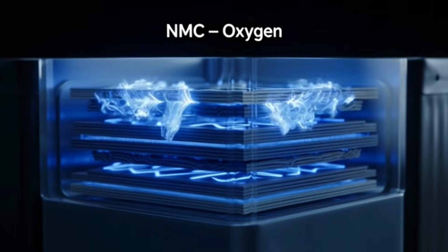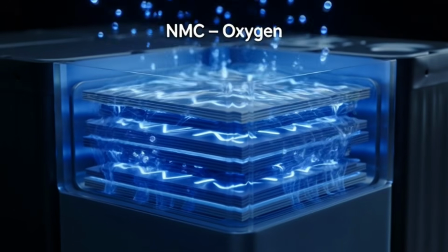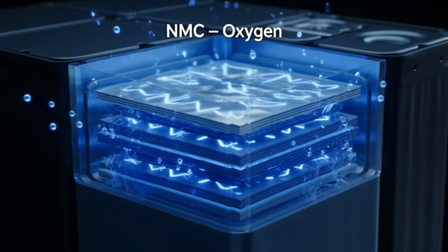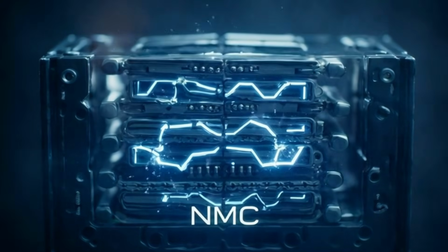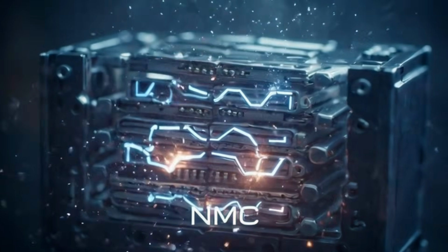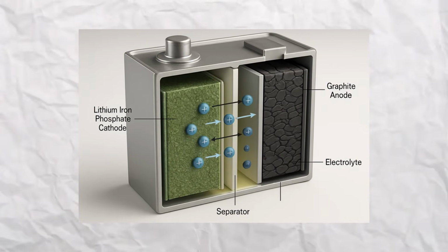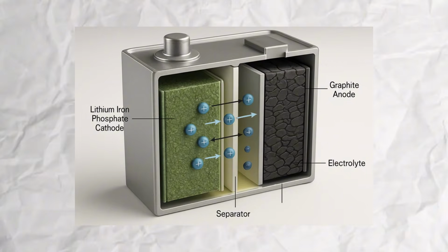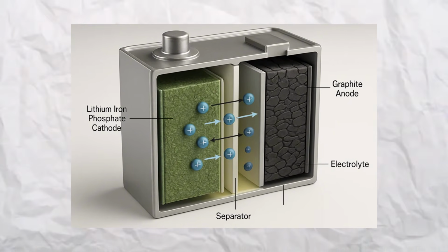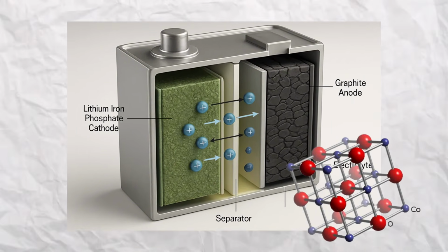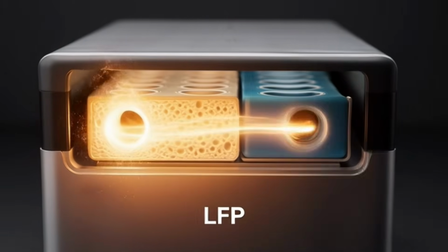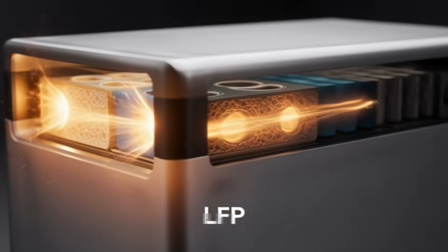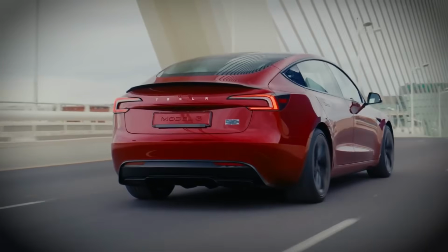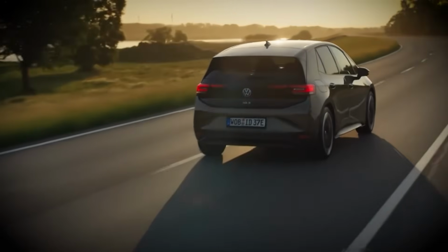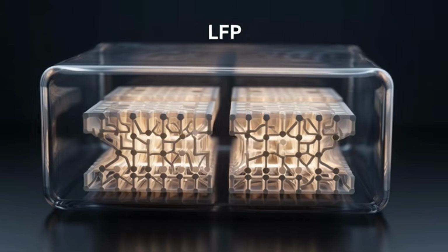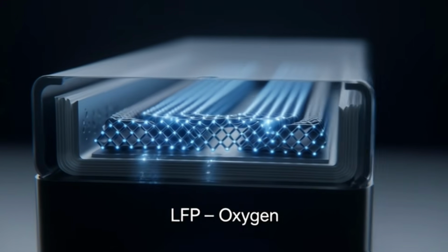When they break, oxygen is released, and when oxygen meets heat and electrolyte in a confined space, you get thermal runaway. Battery fires. The nightmare scenario. LFP uses iron phosphate oxygen bonds, and those bonds are significantly stronger than cobalt oxygen bonds. So when you stress an LFP battery, when you fast charge it repeatedly, when it sits in a hot car, when you're pushing it hard on a road trip, the structure resists. The oxygen stays where it belongs.